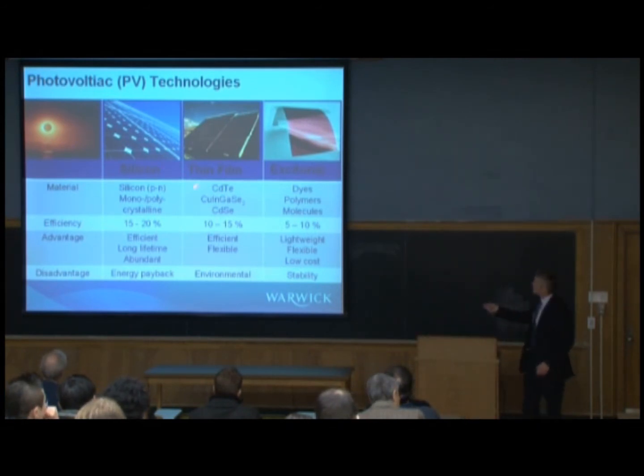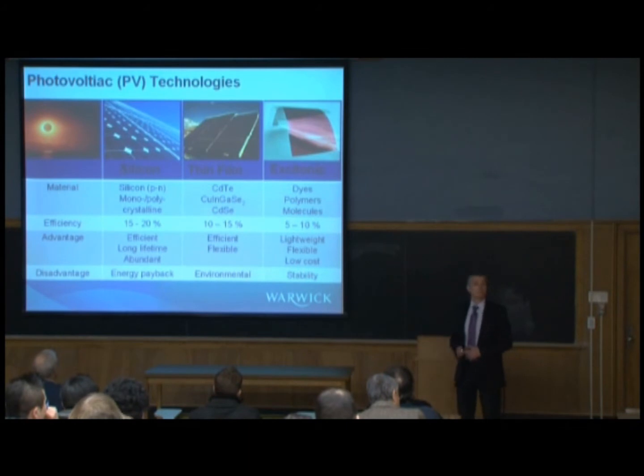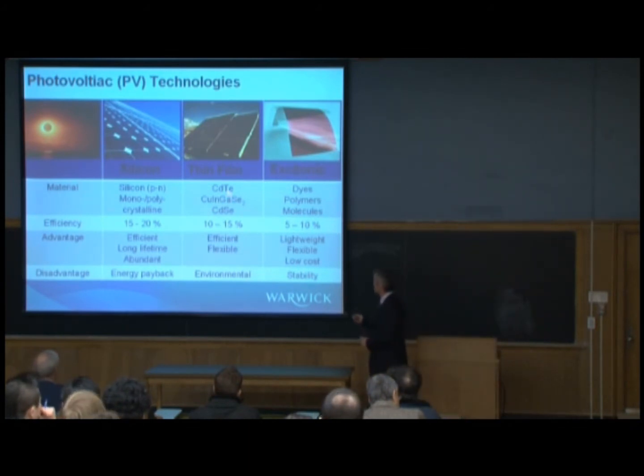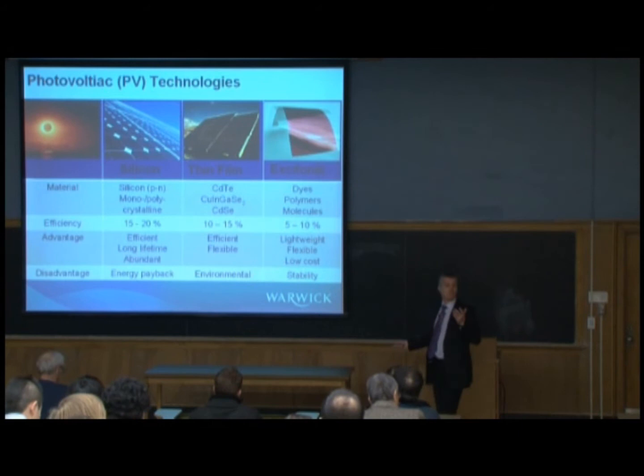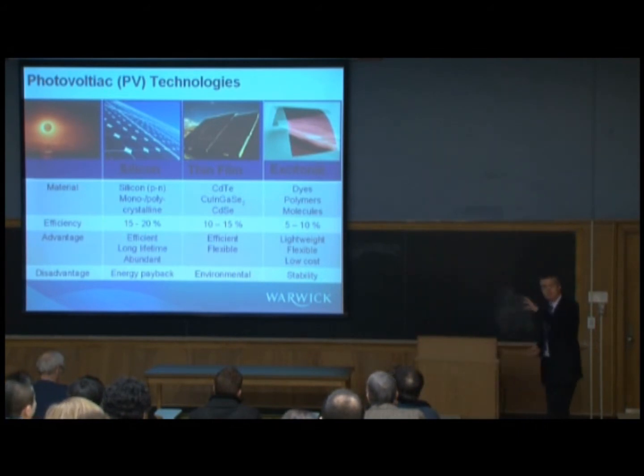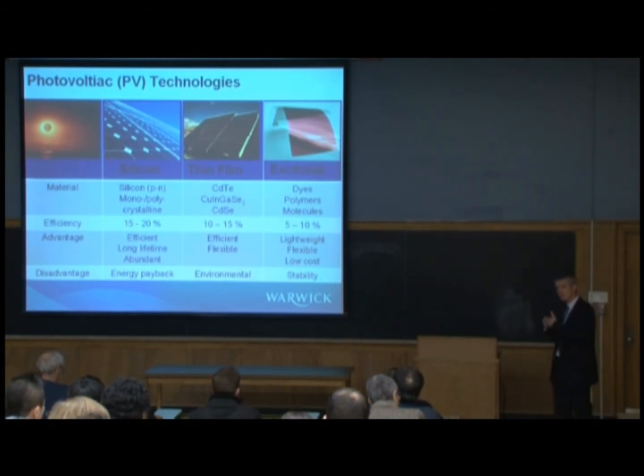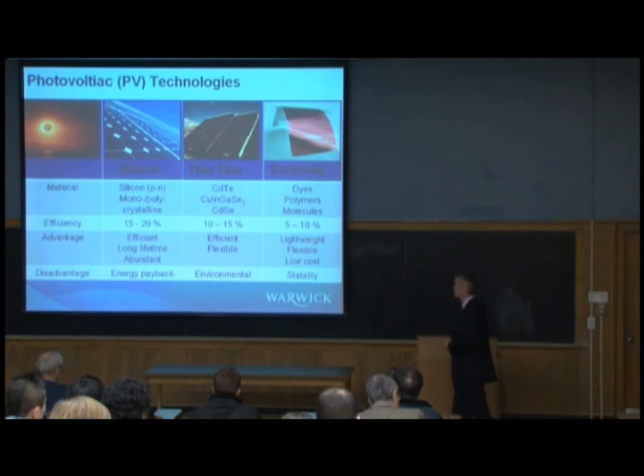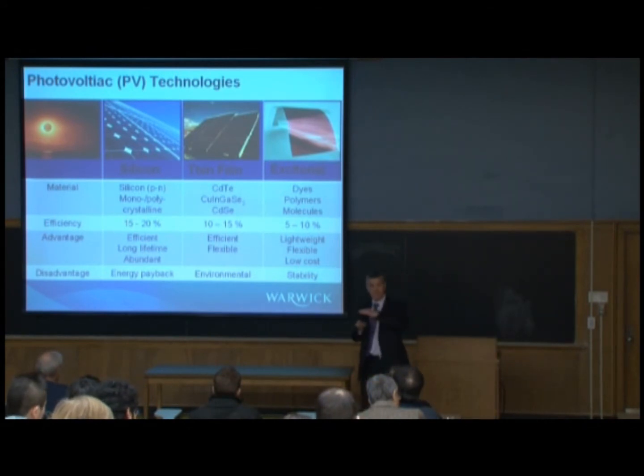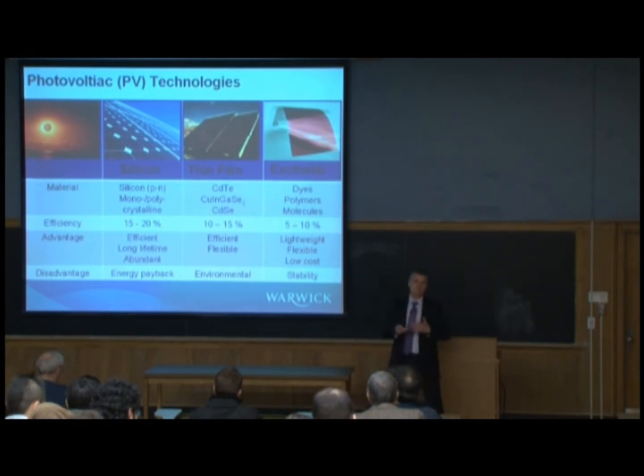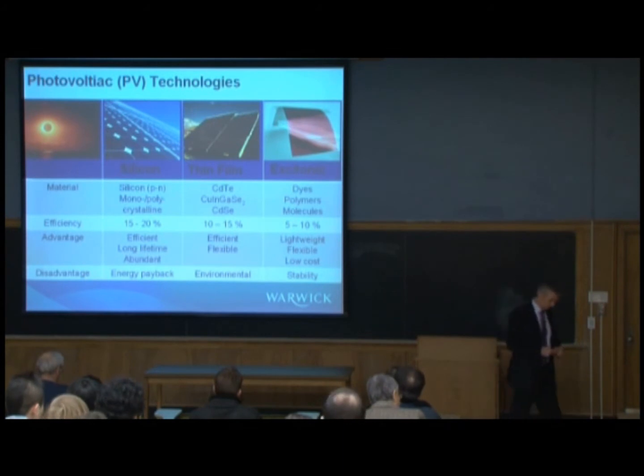The second generation, thin film technologies, also based on inorganic semiconductors, using materials such as cadmium telluride, copper indium gallium diselenide, cadmium selenide. There's also amorphous silicon, which isn't listed there. So there's a bunch of inorganic semiconductor materials that are deposited as thin films. So they use less material. These are thinner devices. A silicon device would be hundreds of microns thick. A thin film device, maybe hundreds of nanometers thick.